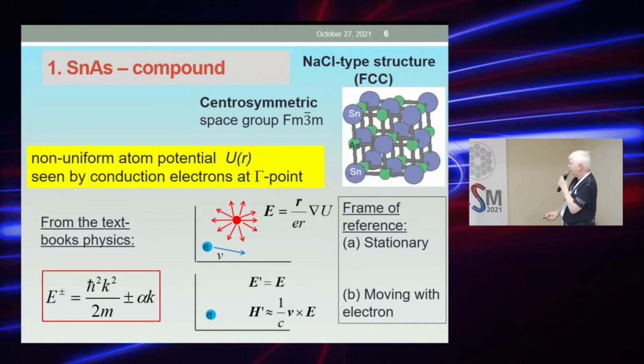and this cartoon refers to textbook physics, but is irrelevant to the tin arsenide. It illustrates that when the electron moves somewhere away from the gamma point in the Brillouin zone, it may feel a gradient of the potential, and this gradient of the potential leads to the Rashba effect, splitting the energy band because of the effective field associated with the Lorentz transformation. Now, this is just textbook physics to illustrate what we were searching for.